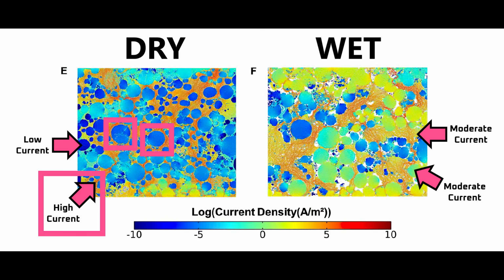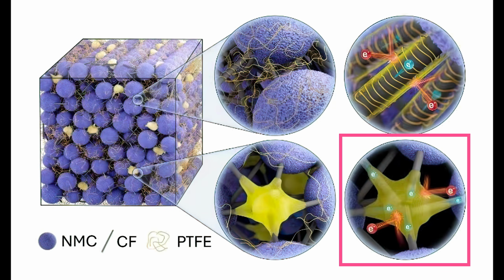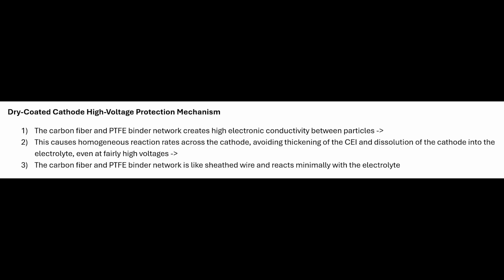As for the proposed dry-coated cathode design, the carbon binder matrix is highly conductive and well-connected, which avoids using the cathode particles as a current pathway. That, in turn, prevents thickening of the cathode electrolyte interface, which means reactions remain uniform throughout the cathode and avoids voltage spikes. Furthermore, the carbon binder matrix functions like insulated electrical wire, which prevents the carbon from reacting with the electrolyte. This combination dramatically reduces high voltage degradation. Again, for clarity, on screen is a summary of how the dry-coated cathode design works.